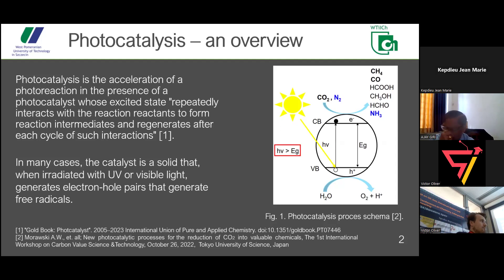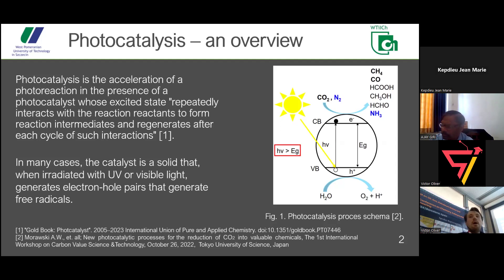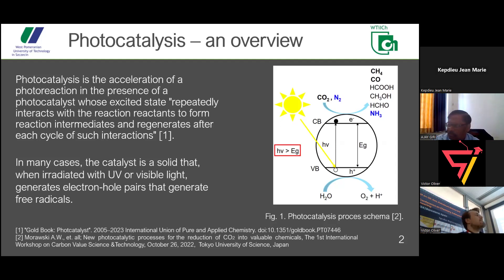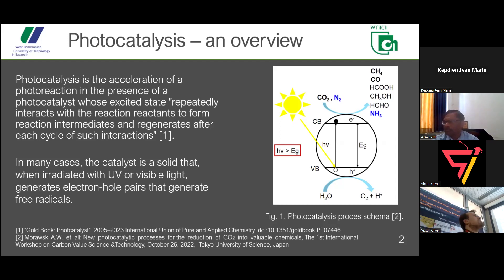Basically, the goal of photocatalysis is to excite electrons from the valence band onto the conduction band, and in this manner create two different charges: first the electron which has been moved, and then the hole which is positively charged and left behind. When there is voltage in the system, both of those charges can be moved around, and therefore it can be very helpful — it can be used in reduction.